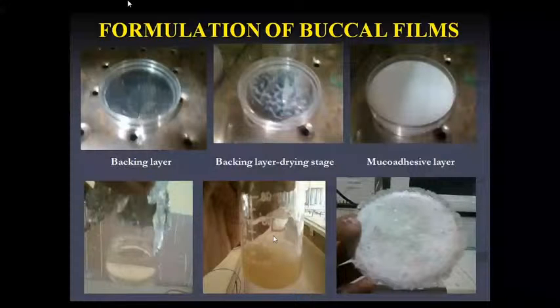Okay. Then this will be transferred over this already pre-formulated backing layer. So what you have to do, once we transfer this, you have to keep it in the oven for maximum 12 to 18 hours at 50 degrees Celsius. So after that, what happens? The water will be evaporated because this layer has this solution. Water usually takes more time to evaporate when compared to the organic solvent.